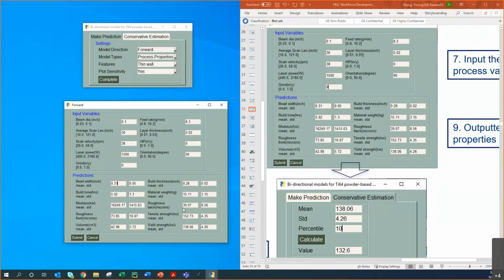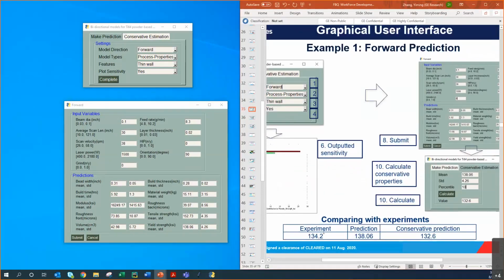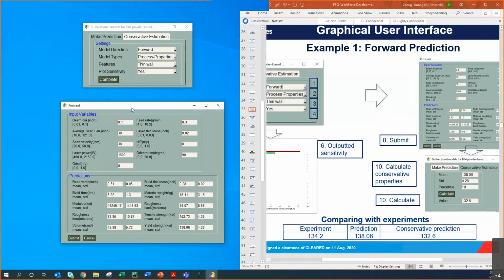And for the validation, we were measuring the yield strength. Now you can see we got the same numbers, about 138 with the standard deviation of 4.26, as they show in the slide. The experimental value is 134 KSI. So our prediction is within about 2 to 3% error for the first validation point.